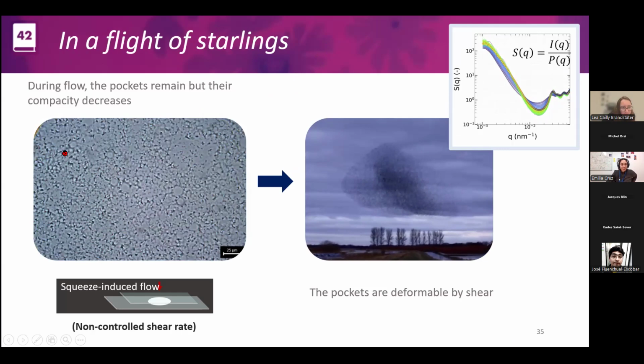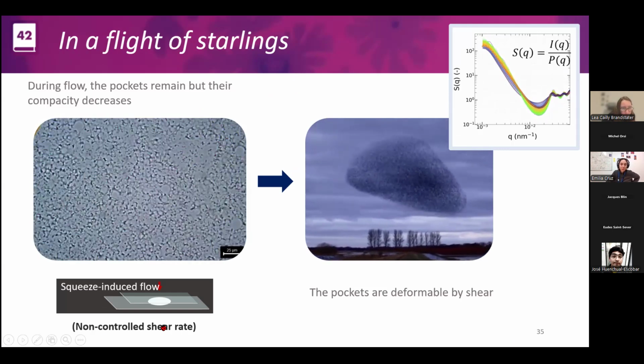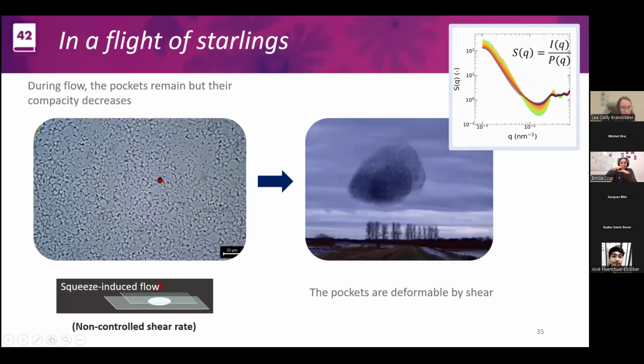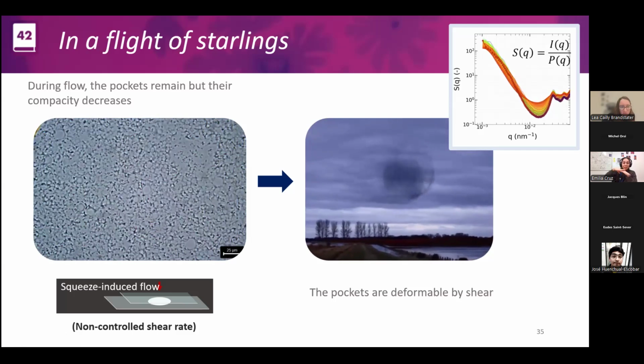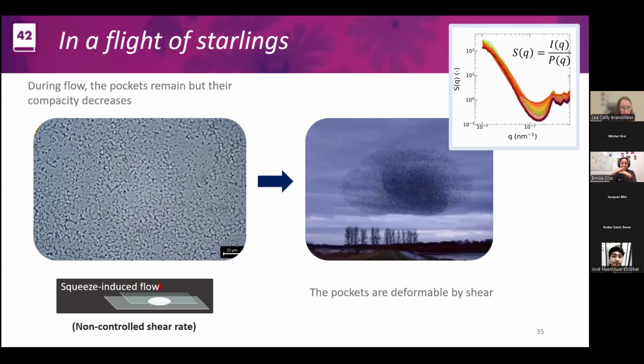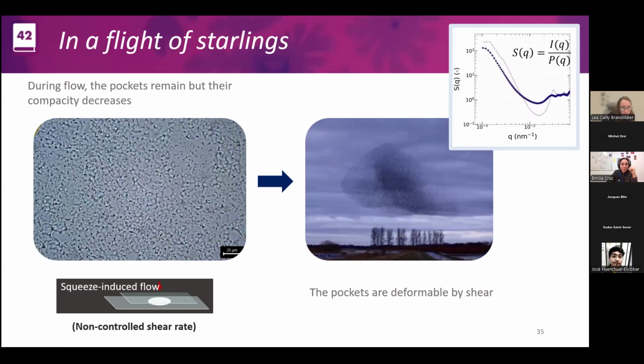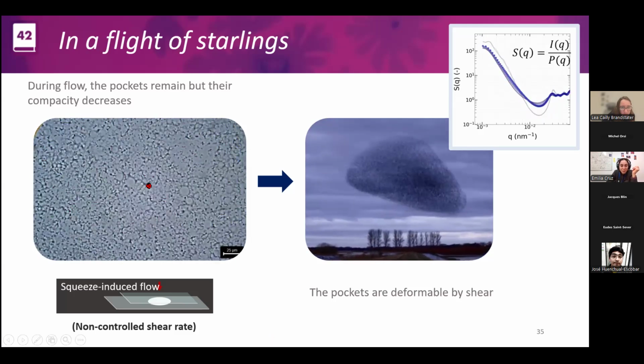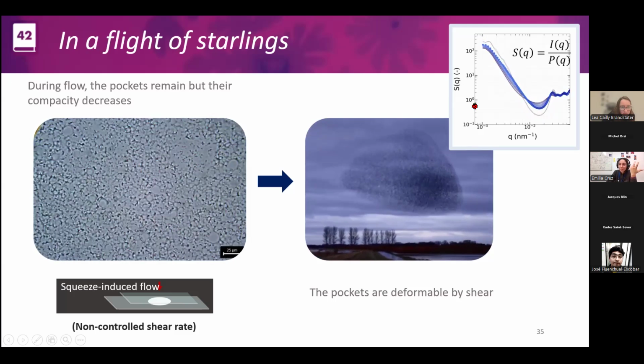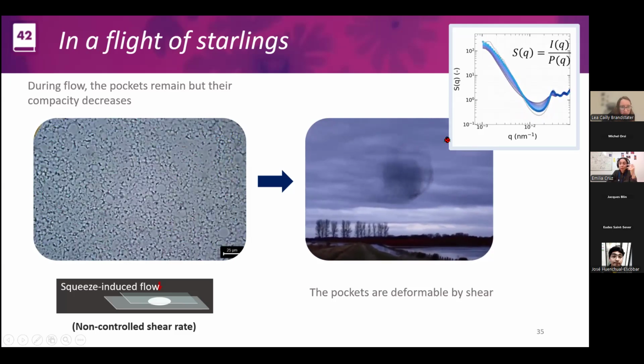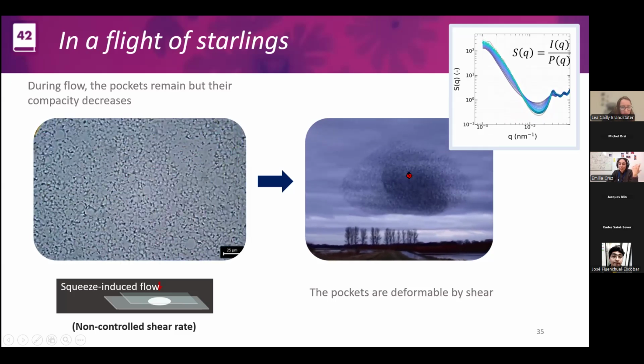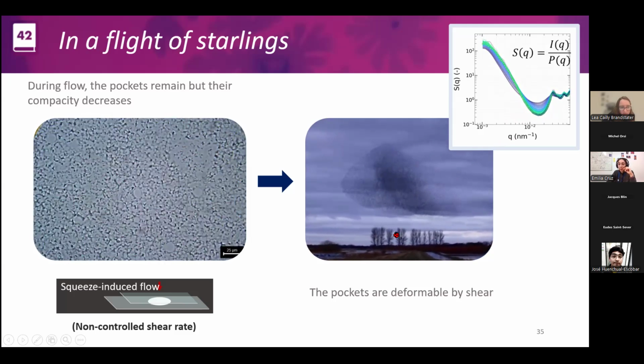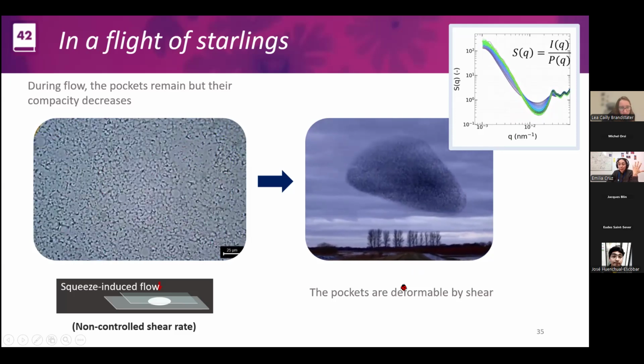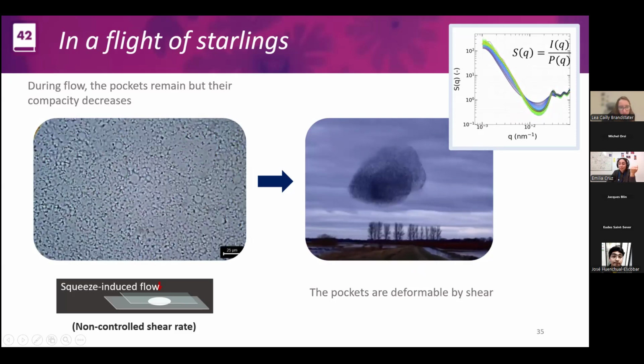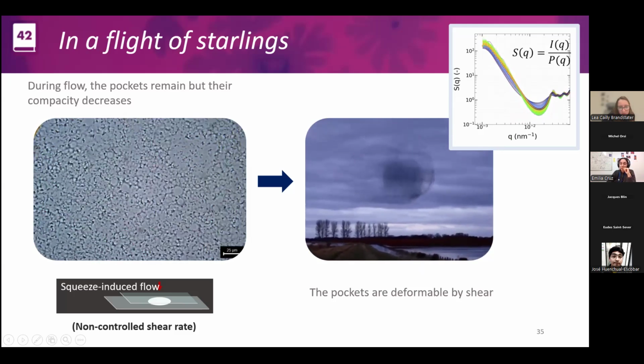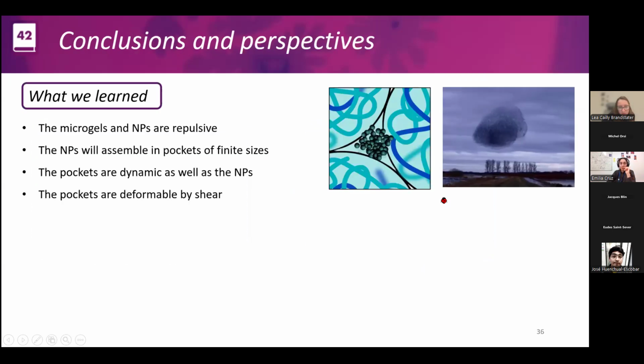So here what I'm showing you is just a non-controlled shear rate experiment that I did. I just compressed a droplet of my sample between two microscope slides. And I just saw that in the microscope and I see that, okay, it's impossible to really know what's happening to that little dot. But now, thanks to the structure factor during the flow, we have a better idea of what's happening during flow. So the pocket remains. The pocket is probably deformable by shear, as we can see, because there are definitely changes in the structure, but it's not a completely collapsed structure.